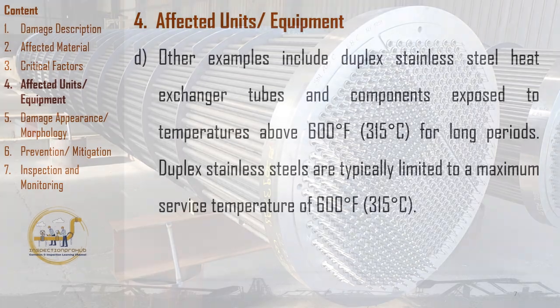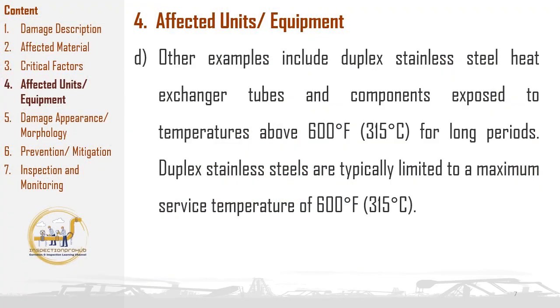Duplex stainless steel heat exchanger tubes and other components exposed to temperatures above 600 degrees Fahrenheit for extended periods are particularly vulnerable to embrittlement. Duplex stainless steels are designed for use below this temperature limit, because prolonged exposure to higher temperatures can disturb the balance between the ferrite and austenite phases, leading to the formation of brittle phases such as sigma phase. This phase transformation reduces toughness and increases the risk of cracking and failure under stress. As a result, the maximum service temperature for duplex stainless steels is typically set at 600 degrees Fahrenheit to preserve their mechanical integrity and corrosion resistance in demanding environments.